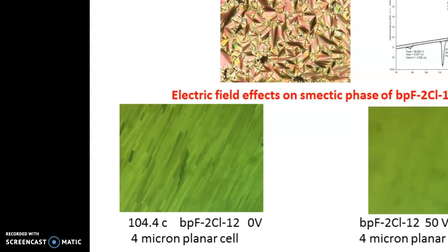I also could observe that substitution by fluorine decreased the melting point of the compounds, which is again very much required for any compound to be used in LCD devices. Also, increased chain length suppressed the nematic phases. And one of the most important findings from my research is that the lateral polar groups on the central core tend to suppress mesomorphism.